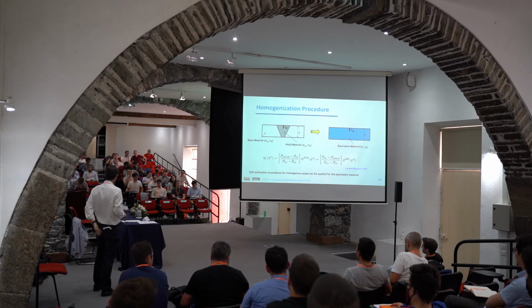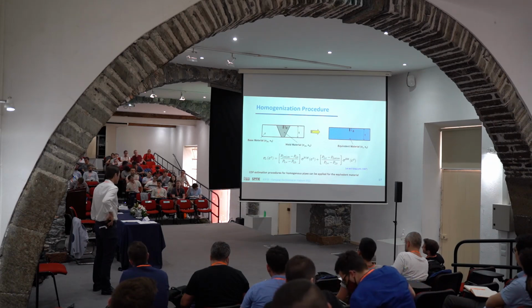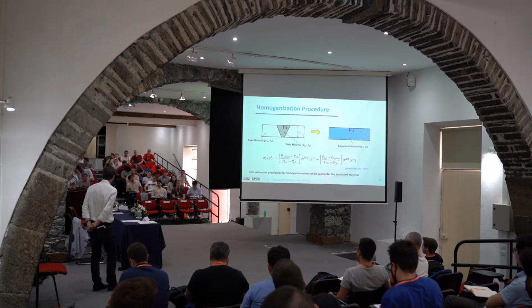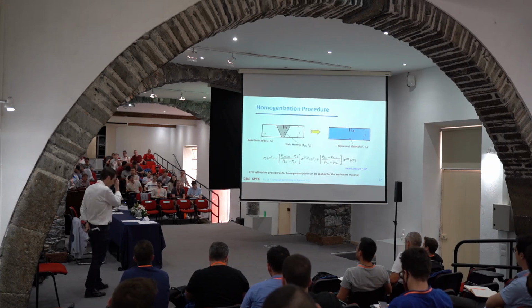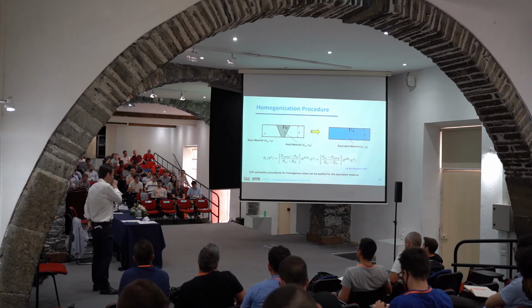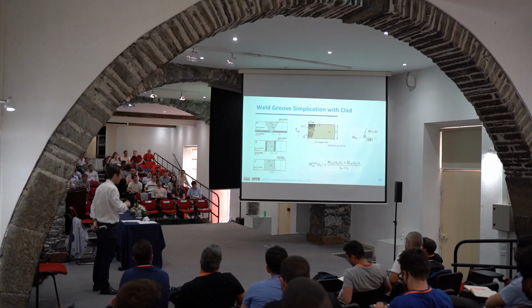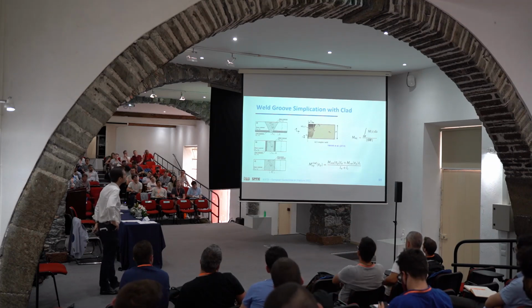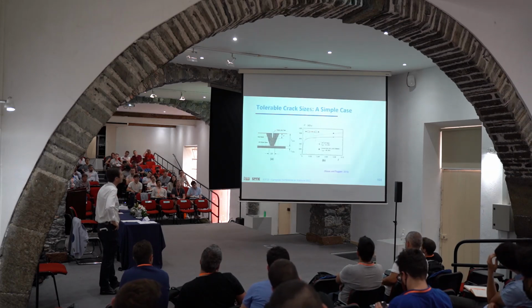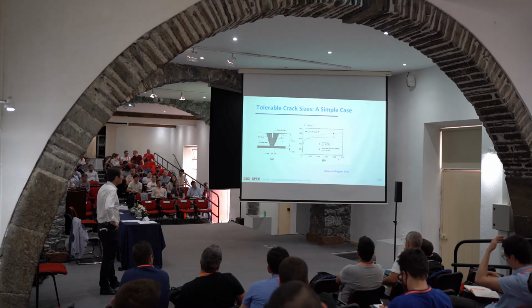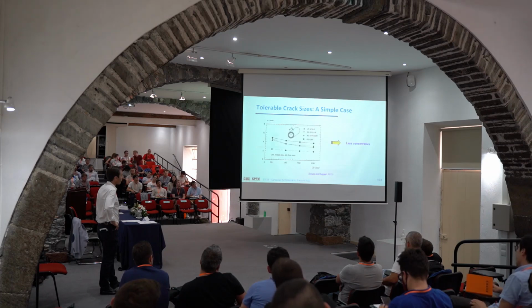It works like this. You have the similar weld, you apply load, you measure displacement. So what would be the homogeneous material that would give you the same displacement with the same applied load? That's the idea behind this. It's a little complex. We use limit load analysis, slip line calculations, et cetera. What's important is this: in a simple case like this, we have the stress strain curve, and this is what we would get. The tolerable crack size. Just to give you an idea, this is my last slide.